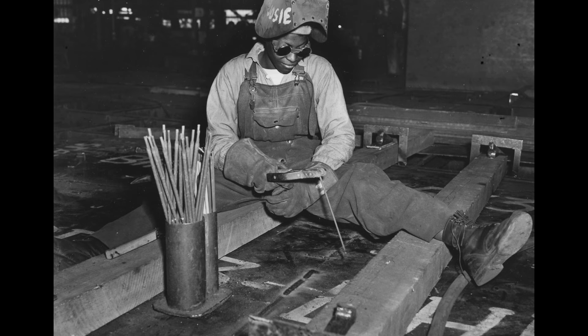Traditional riveted ships hadn't suffered this fate, and the reason revealed why welding, for all its speed, was inherently risky. Riveted construction is naturally discontinuous. Each plate is an independent element. A crack that begins in one plate stops cold at the riveted joint. The overlapping plates and mechanical fasteners act as natural barriers. Welded ships, however, are continuous. A crack in one panel can run unbroken through hundreds of feet of seams. The same efficiency that made welded ships faster and cheaper also made them dangerously vulnerable.